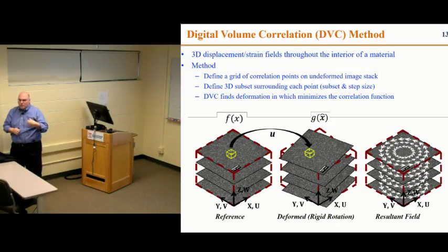What I'm showing you here is what we've done to get good images. And that's why I call this a model composite. We have made it this way so that it works both with the tomograph and with the image correlation and so on. If you take a random material, it may not work exactly. So you have to play with the intensity of the machine, the size of the beam, the magnification, and so on. There's a lot of things that you have to do to get the image to look proper before you can actually do an image correlation, right?